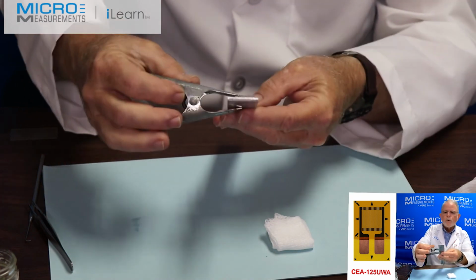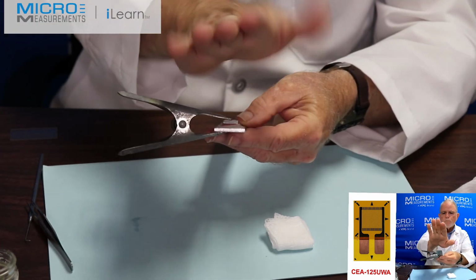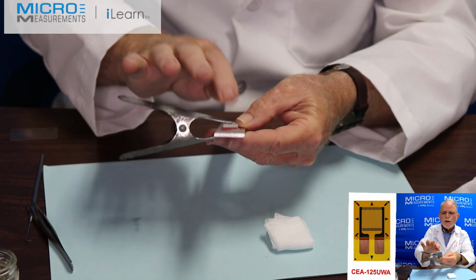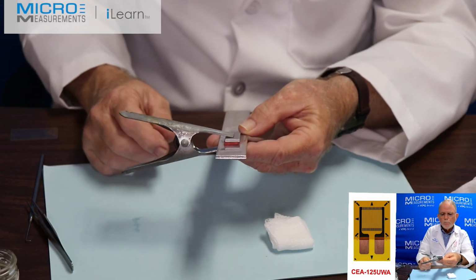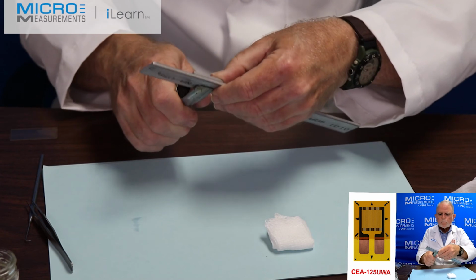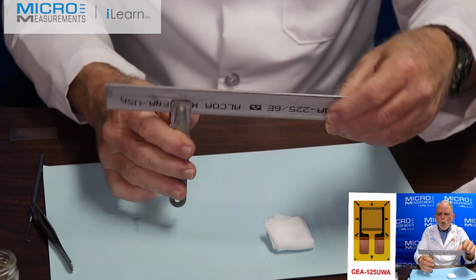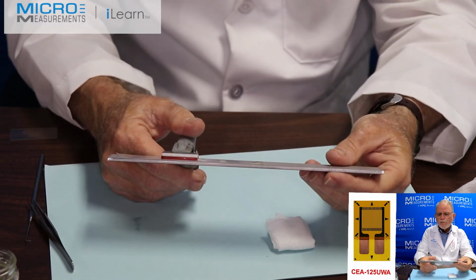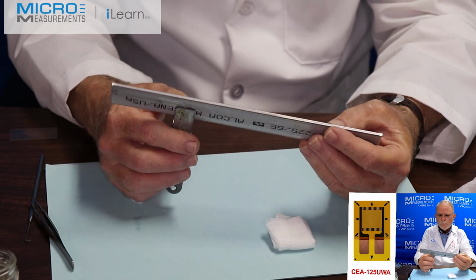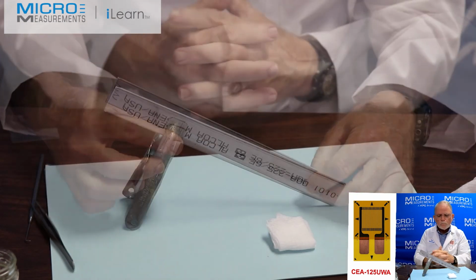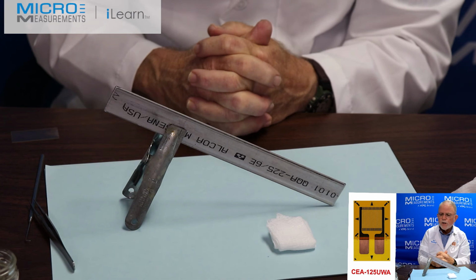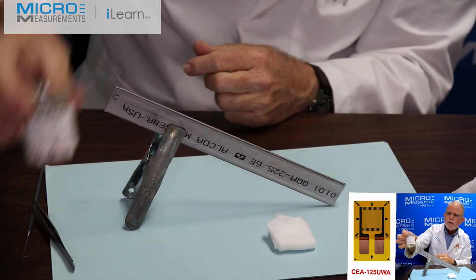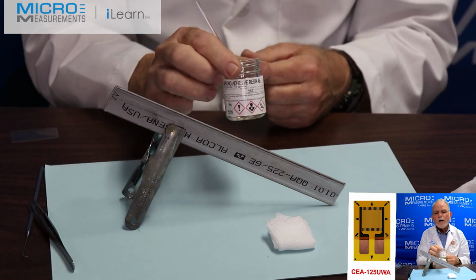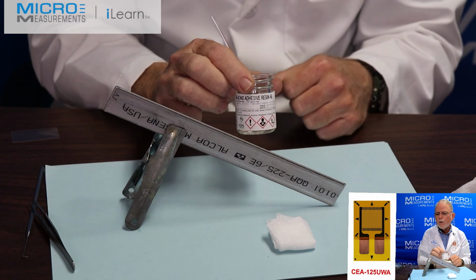paying attention, looking down the beam to make sure that the silicone gum pad and the aluminum backing plate are parallel to the beam that's being clamped up, and also double check that it's evenly clamped in the lateral direction also. And at this point, we have completed an installation using AE-10, a room temperature curing adhesive system, recently rated up to 400 degrees Fahrenheit on the top end,